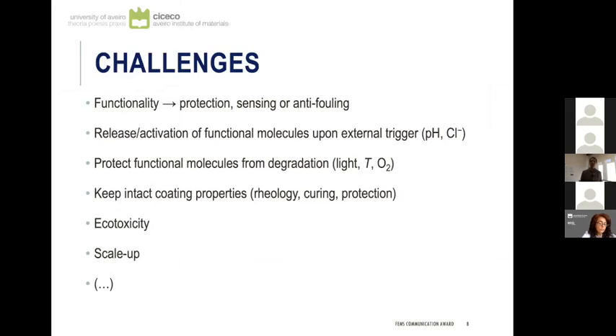There are several challenges associated with trying to modify coating for target functionality. First of all, the way the compound should act. If it's for active protection, it needs, for instance, to be released and transported to the metal interface and work on the interface. If we are talking about corrosion detection, for instance, it needs to signal a change, for instance, presence of water, or change in pH, or presence of oxidized species, or the anti-fouling, like the release of the compound to the